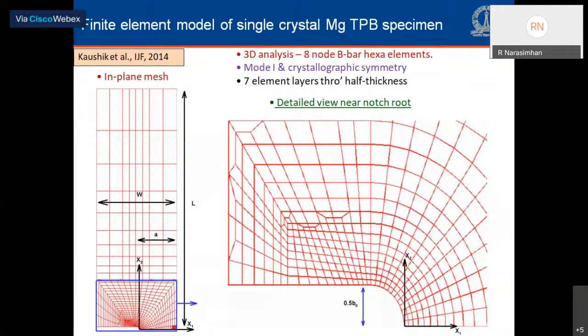In the in-plane views of the mesh, as well as the detailed view near the notch root, as shown here, we model half the specimen through about 7 element layers. And these get increasingly thin as we approach the free surface in order to capture the steep stress gradients as you approach the free surface.